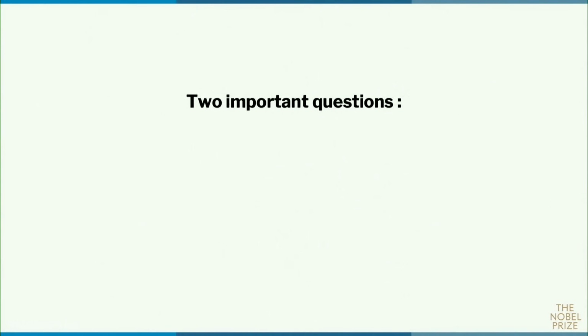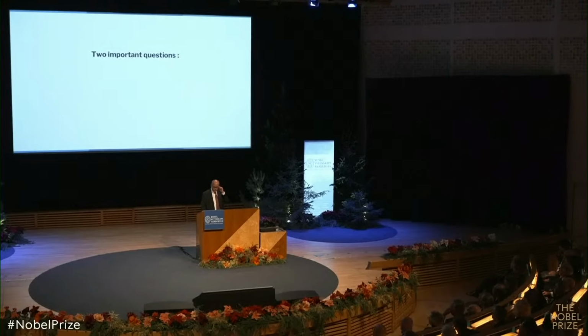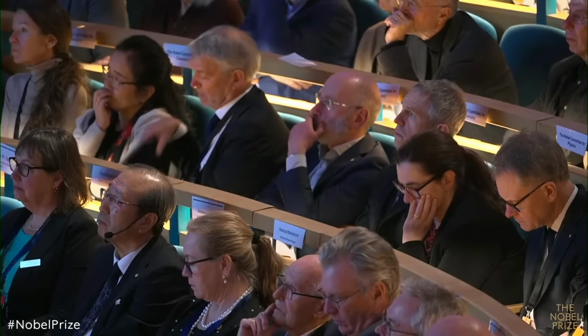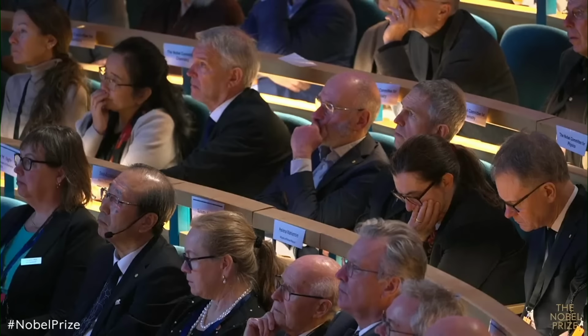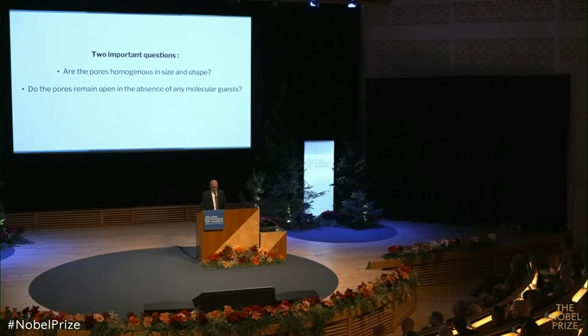So the report by Susumu raised, in my mind, two important questions. One, are the pores homogeneous in size and shape? Pressurizing compounds, studying gas adsorption under high pressure, does not give you this answer. Okay, so that was a question we needed to answer. And then we also had to answer this question: do the pores remain open in the absence of any molecular guests? Those are two very, very important questions.